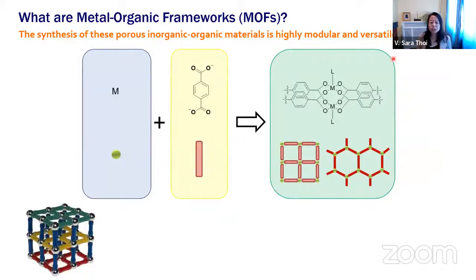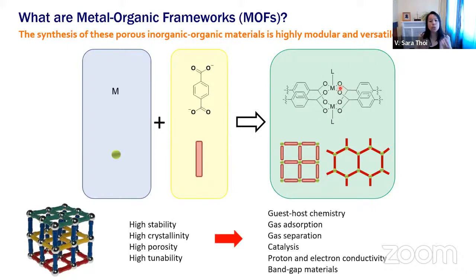So I want to first introduce what metal organic frameworks are. Metal organic frameworks, or MOFs, are materials composed of both metal ions or metal clusters with organic linkers that self-assemble into these really beautiful 2-dimensional and 3-dimensional materials that are based primarily on the coordination environments of those metal ions. These very unique structures have high stability, very high crystallinity, and really are known for their high porosity and synthetic versatility that has led to a whole host of different applications, most notably in gas adsorption and separation. But today, I hope to show you that we could also use these metal organic frameworks for electrochemical devices.